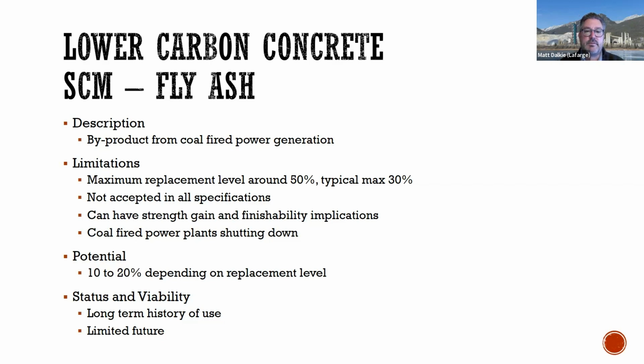Replacement levels max out at around 50%, but typically around 25 to 30% maximum. Again, not necessarily accepted in all specifications. You need to be aware of strength gain and finishability implications. And if you're looking at very, very high levels of SCM, you also need to be aware of what the curing requirements are for that concrete as well. Now, what's happening is coal-fired power generation is shutting down, so that means the availability of fresh fly ash is becoming more of a challenge.